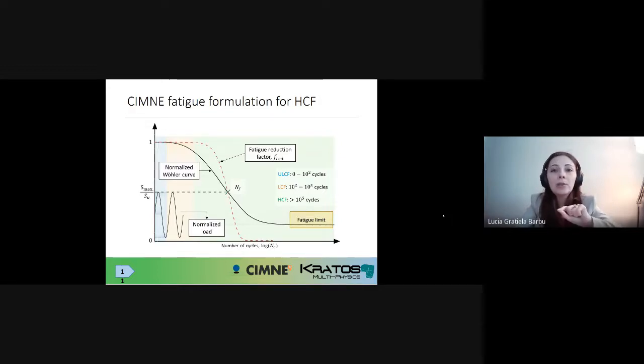When we add the fatigue reduction function into this equation, we are obliging it to respect two different conditions. It should begin at a level of 1, which would be the static tensile strength of the material. And this function necessarily has to pass through this intersection point over here, which tells us that we have lowered the strength of the material sufficiently that we are crossing the level of maximum stress, and this is when we are breaking our specimen at that specific material point. The evolution between these two points will depend on the material parameters that we will have to calibrate.